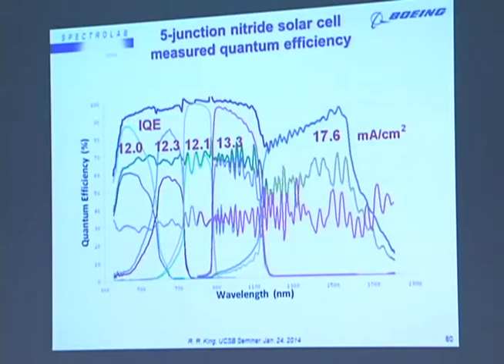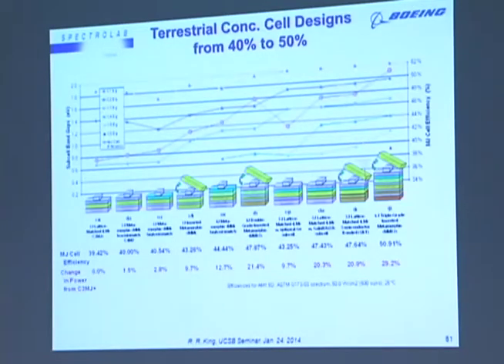This is the quantum efficiency of such a 5-junction cell, where this subcell 4 is the dilute nitride cell. This is the top cell, cell 2, cell 3, the dilute nitride cell. So you can see we're achieving very good quantum efficiencies even in that dilute nitride material. This is the germanium bottom cell, and getting good current densities in all of them.